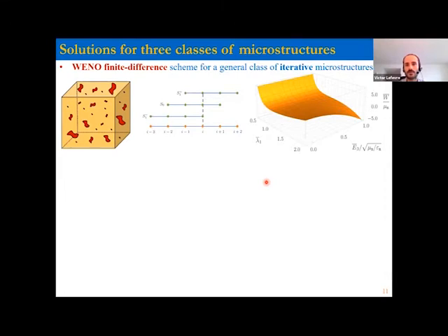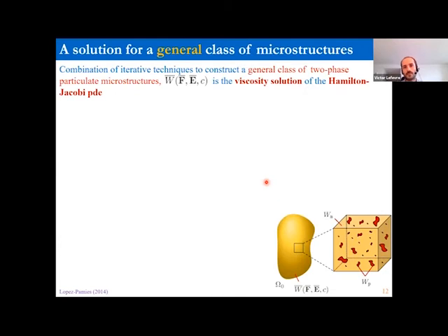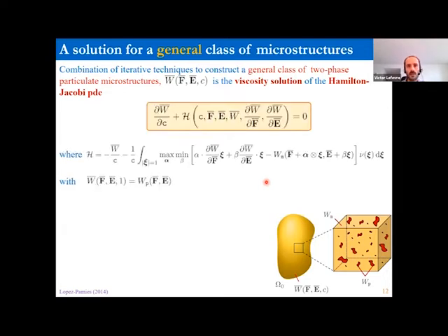These are constructed using an iterative process. And so, as I mentioned, we put the particles and the matrix where we want, and we do that in such a way that W bar, the macroscopic response of this synthetic microstructure, is the viscosity solution of a Hamilton-Jacobi partial differential equation. So the PDE is given here, H is the Hamiltonian, and you have an initial condition given at 1 here. I'm going to comment on that in a second.